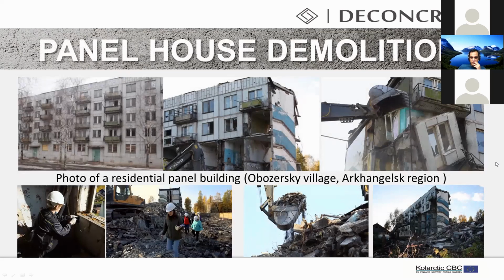So in our case study, we obtained our sample from a demolished residential panel building in Arkhangelsk. As you can see on this slide, it was demolished by a crane, which is not very efficient and not environmentally healthy, but it's the most common practice in Russia. As you can see in the photos, we visited this place and took about 100 kilograms of different samples from that object. We also went inside that house before it was demolished and measured the strength of the different structures by the shock impulse method.